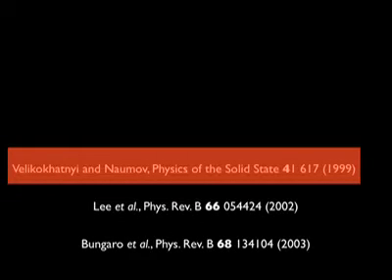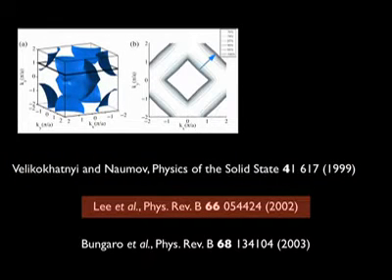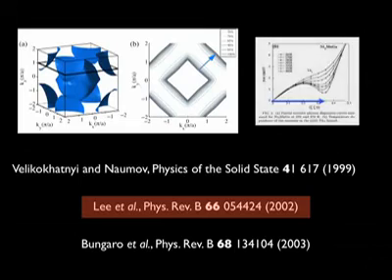Early band theoretical work carefully investigated the Fermi surface nesting, but it was Lee and co-workers who first considered the effect of temperature on the exchange splitting and hence the nesting properties of the Fermi surface, showing that the nesting vector at a temperature close to the pre-martensitic transformation matched the location of the phonon anomaly.